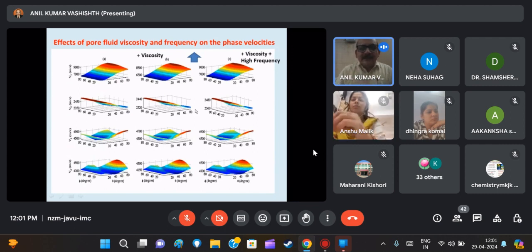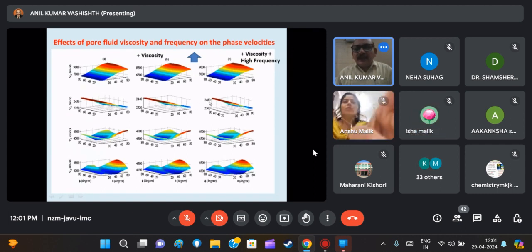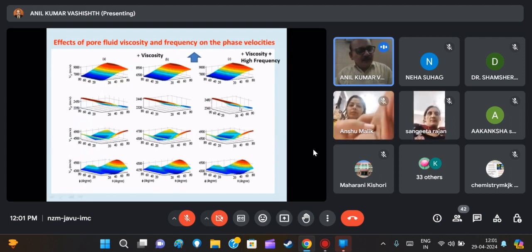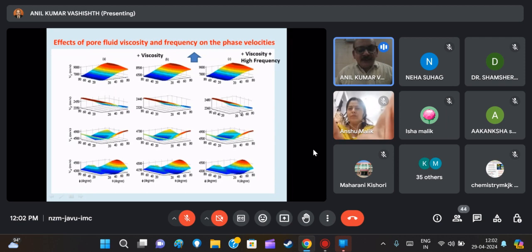Here we have shown the effects of viscosity in this class, and as expected, the wave velocity decreases for all four waves when the viscosity effect was included in class B. When viscosity and high frequency both were taken into consideration, we can notice the second wave, the second sound wave, shows a significant variation towards an increment. It means this wave is going to be significant as far as ultrasonic waves are concerned.